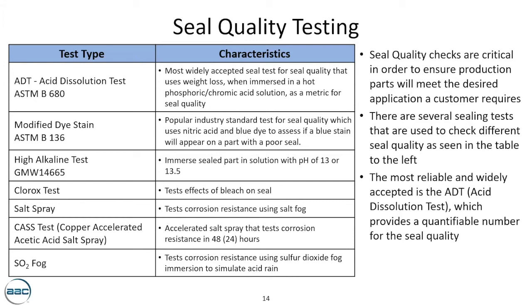The pH of this solution is usually between 3.1 and 3.3, and this test is done for corrosion resistance for 24 to 48 hours. The last one is sulfur dioxide fog, which is used to mimic acid rain.